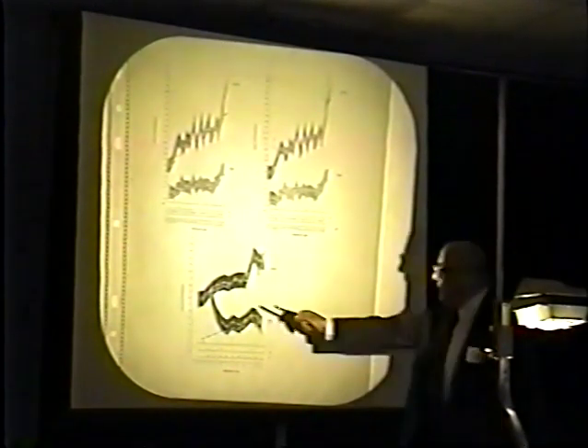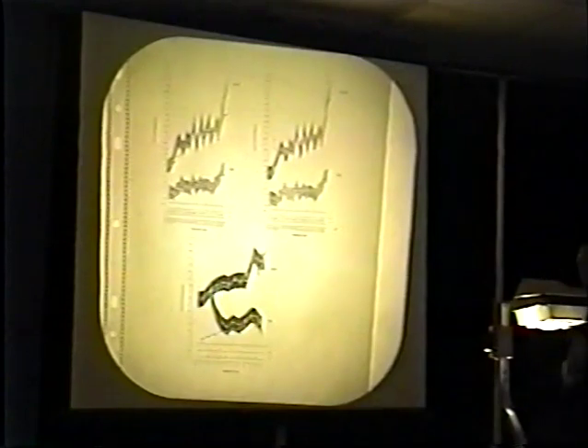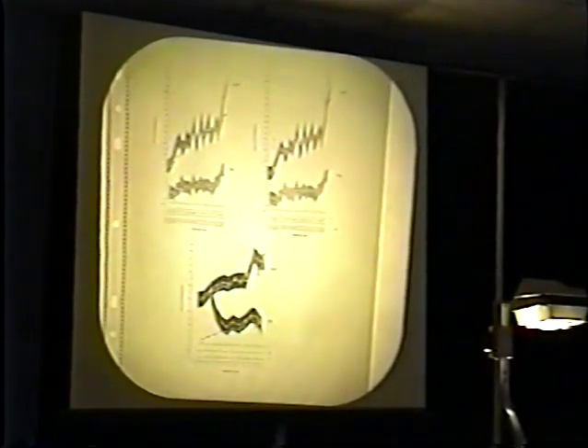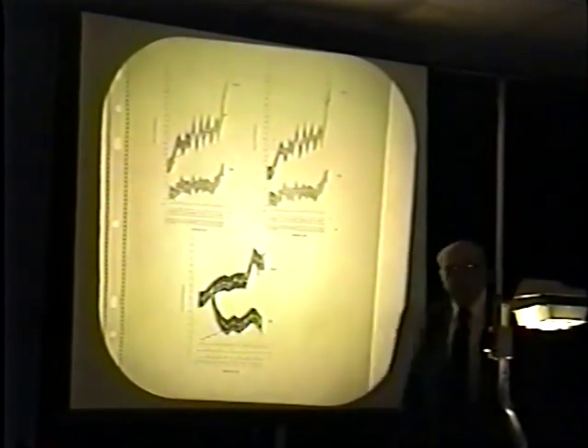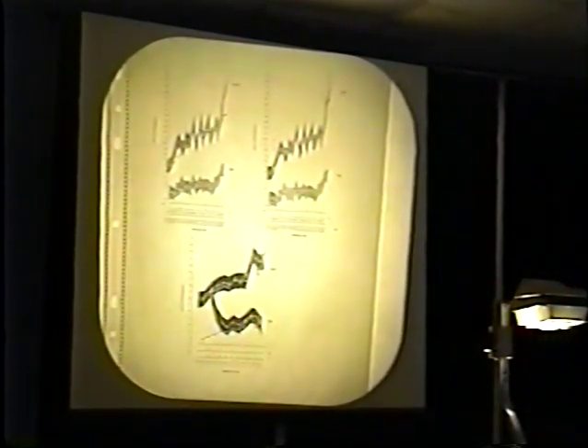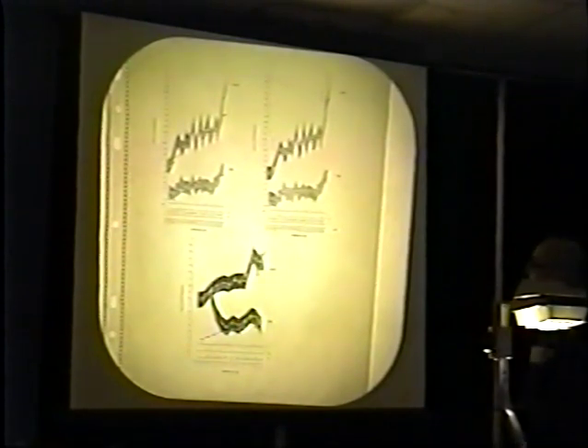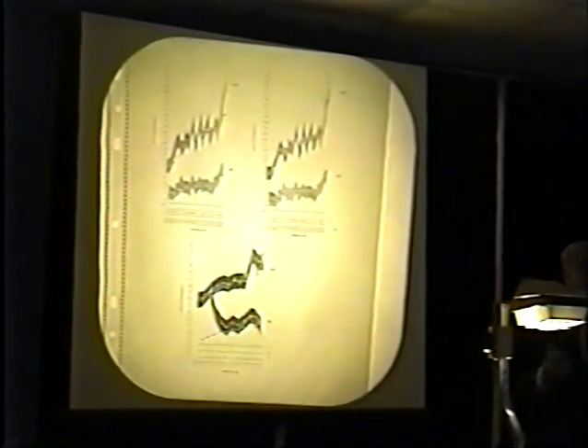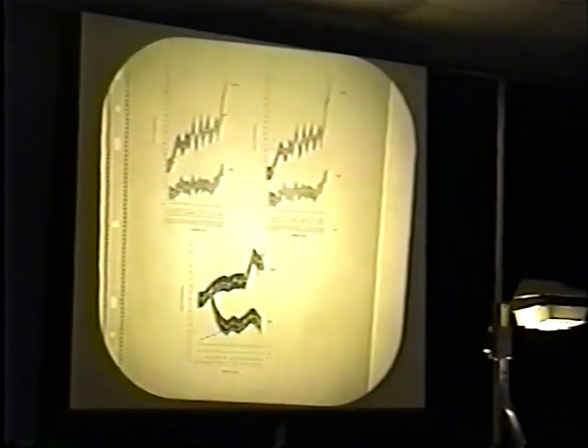You can see that the liquid phase follows exactly the computed values. What does it mean? It means that at least we have 2 extreme cases of the interactions between the produced tritium and the electrolyte. In the first case, it goes into the solution and then into the gas phase. In the second case, it simply goes directly into the gas phase. Now, in practice, in the other cases, normally what you see is both ways, part goes here, part goes there. So essentially, those are 2 critical cases.